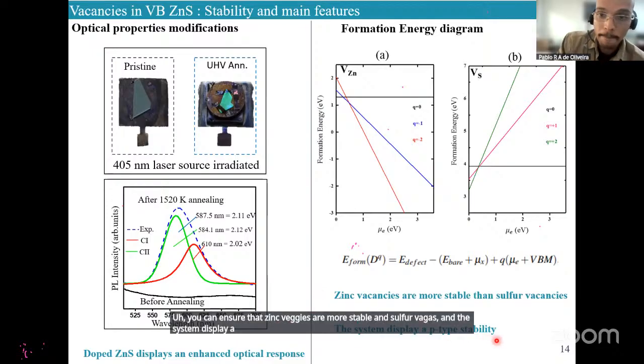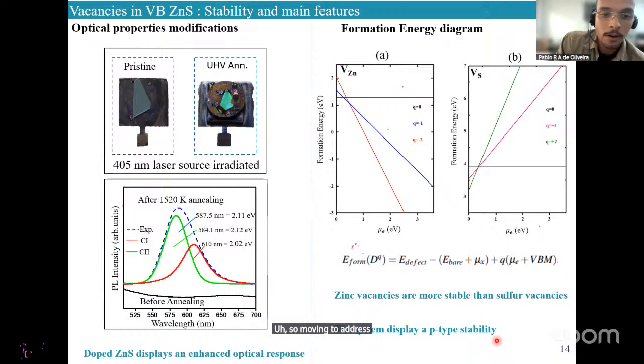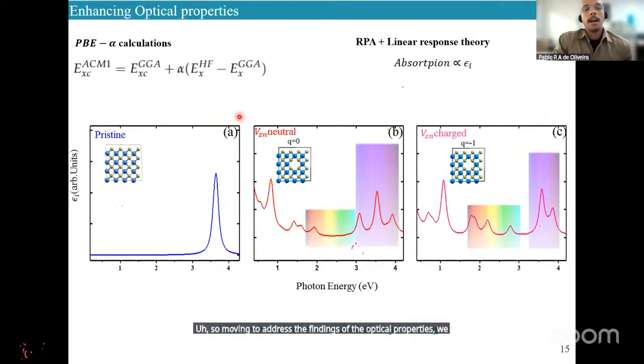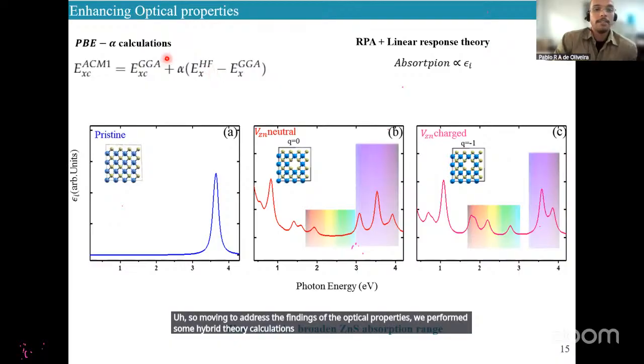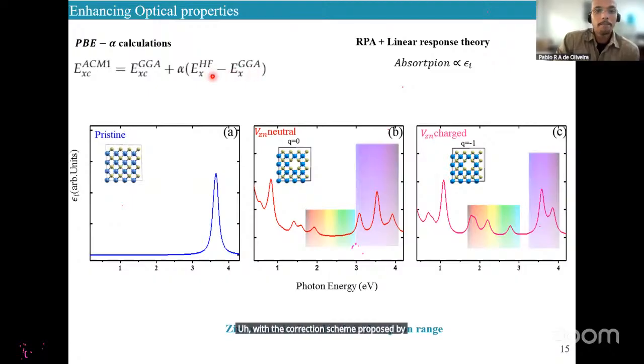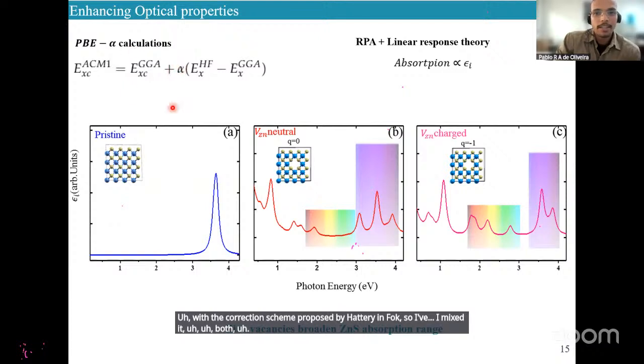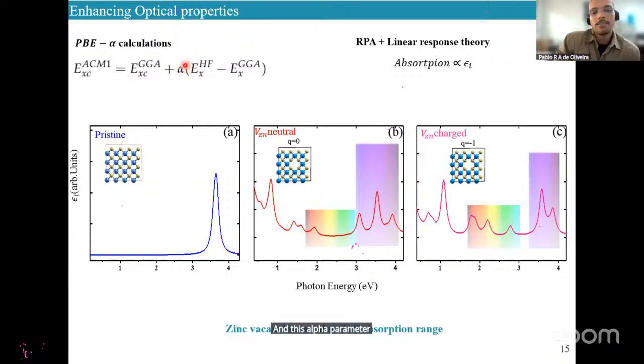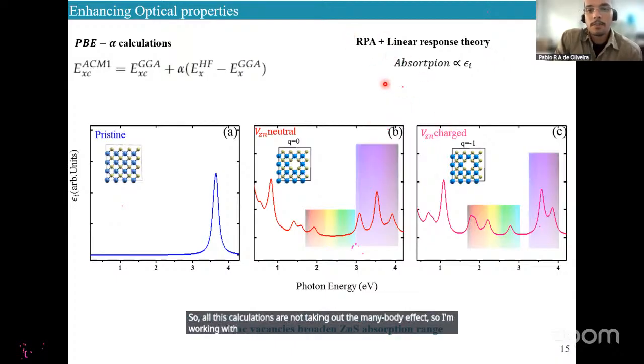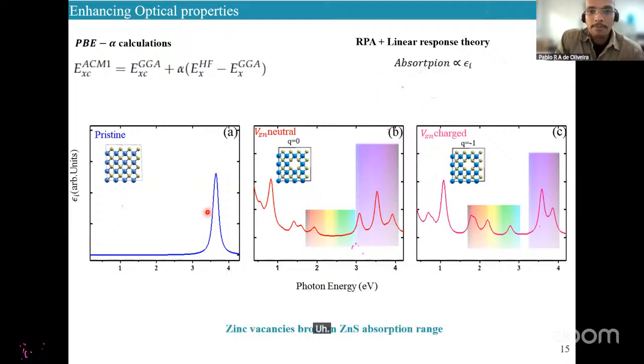So moving to address the findings of the optical properties, we performed some hybrid theory calculations. Basically, I combined the GGA method with the correction scheme proposed by Hartree and Fock. So I mixed both functionals, and this alpha parameter was fitted to match the experimental band gap of 3.6 eV. All these calculations do not take into account the many-body effect. So I'm working with the RPA and linear response theory, where the absorption is proportional to the imaginary part of the dielectric tensor.